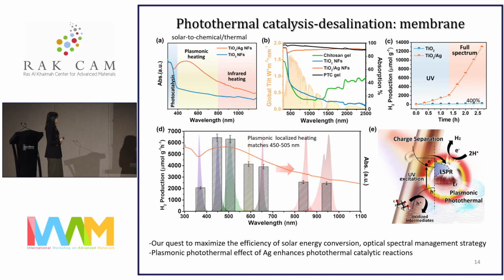In our quest to maximize the efficiency of the solar energy conversion, we have employed an optical spectral management strategy to promote the designated solar to chemical or solar to thermal conversion. What I mean by that is that the high energy UV photons are designated for photothermal catalytic redox reaction, and the lower energy visible photons are designated for plasmonic heating, while the lowest energy infrared is absorbed by the gel for photoheating as well. With the addition of visible and IR illumination, we can see that the hydrogen performance has improved by 400%.